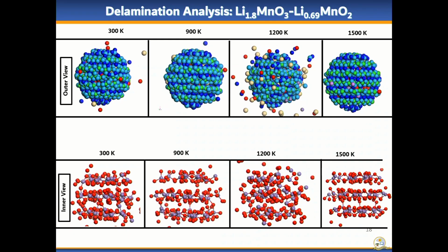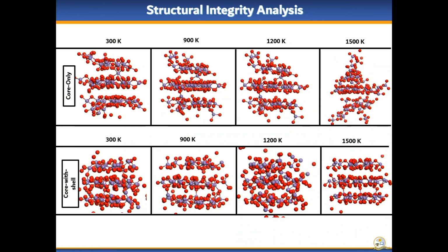Then at 900, it looks intact again. Then at 1.2, it seems a bit dissociated, with some manganese migrating onto the lithium layer. But the interesting thing is what we saw at 1.5, where we were able to retain the structural integrity again for our core material. This is something that we really desire, and we are yet to evaluate it for other concentrations. Then we ran our core system alone, and we wanted to see what kind of structural changes it undergoes.